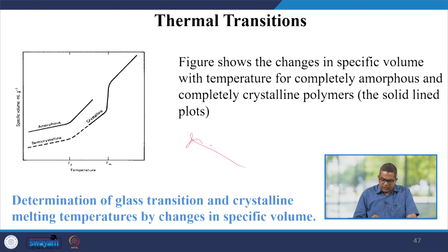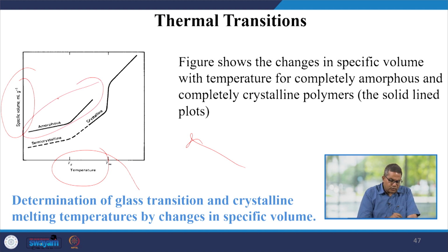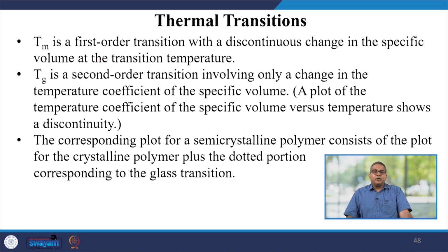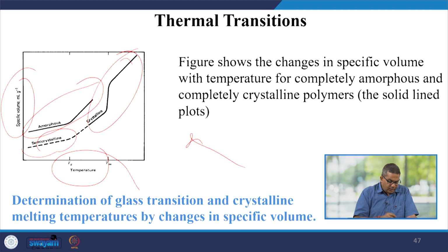This figure shows the changes in specific volume with respect to temperature for a completely amorphous and a completely crystalline polymer. You see here the amorphous, this is the semi-crystalline, and beyond this, the crystalline one. Tm is a first order transition with a discontinuous change in the specific volume at the transition temperature, and the glass transition temperature is a second order transition involving only a change in the temperature coefficient of specific volume. A plot of the temperature coefficient of specific volume versus temperature shows the discontinuity. The corresponding plot for the semi-crystalline polymer consists of the plot of a crystalline polymer plus a dotted portion for the glass transition. Here you see.